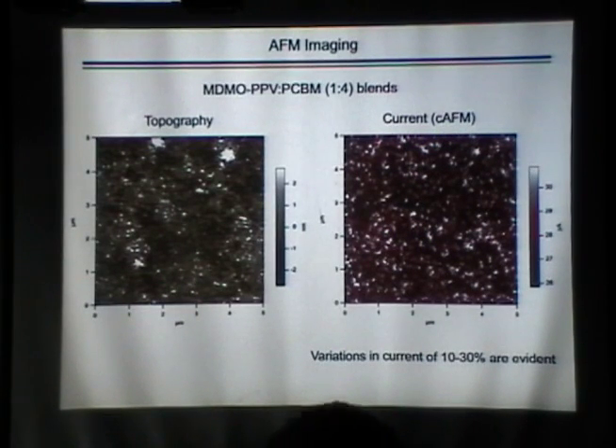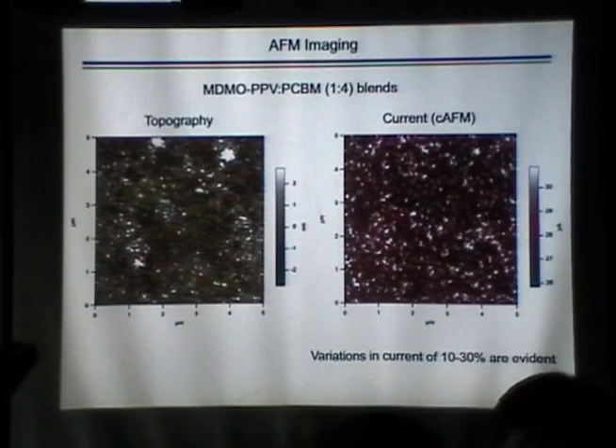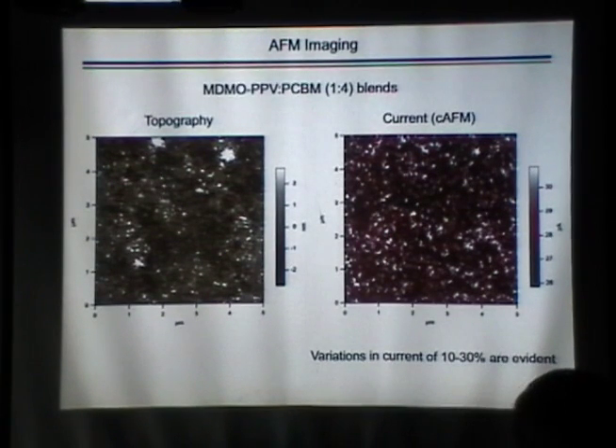And what we find actually is that there are very large variations in the photocurrent across the surface of the film. Sorry, not photocurrent, in current. So in this measurement, we take the AFM tip, we bias it at a couple volts, and we just run it over the surface and measure the current.